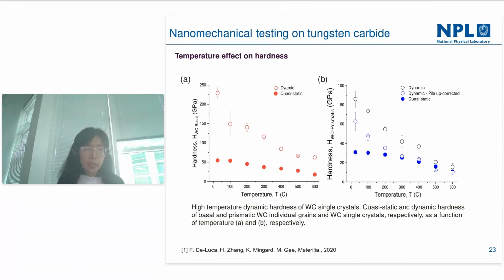So here we plotted the hardness and the dynamic hardness of the two tungsten carbide grains, and to summarize the image, we can see there is strain rate dependent behavior regardless of the orientation of the grains, revealing higher hardness at high strain rate at temperatures up to 200 for both, and across the entire range of tested temperatures for the prismatic and basal orientation.